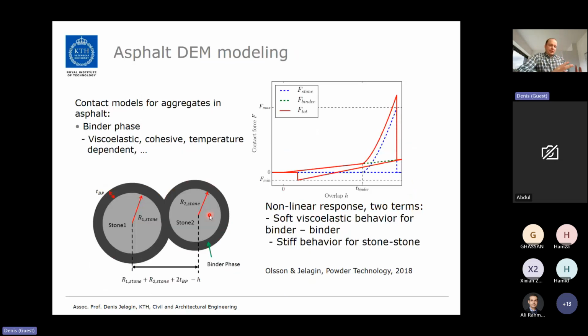Now, that was for the contact law between two aggregate particles. In case of asphalt, the story becomes more complicated because in addition to aggregates, we also have a viscoelastic phase. And for that, we propose a two-term law based on elastic aggregate particles coated with viscoelastic binder phase, published in Powder Technology in 2018.